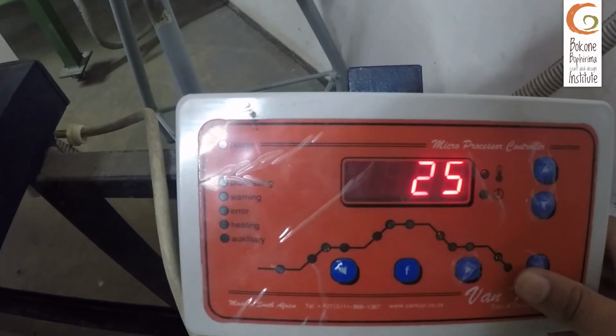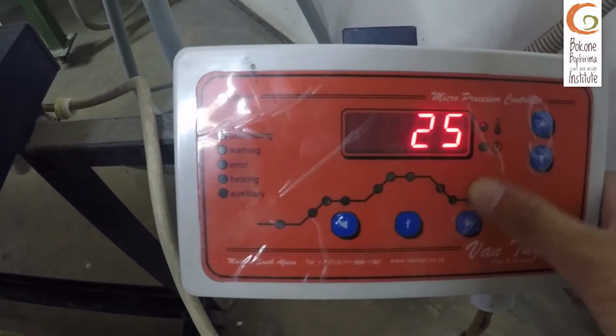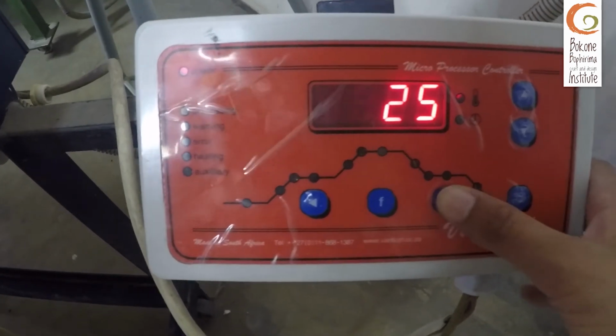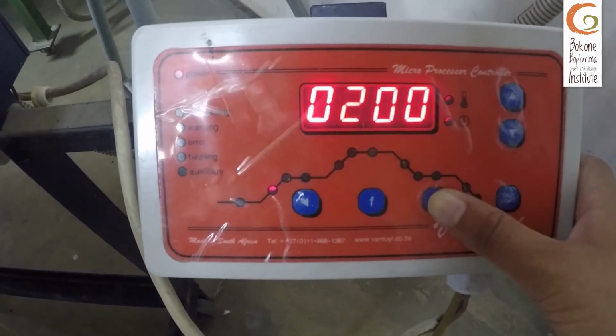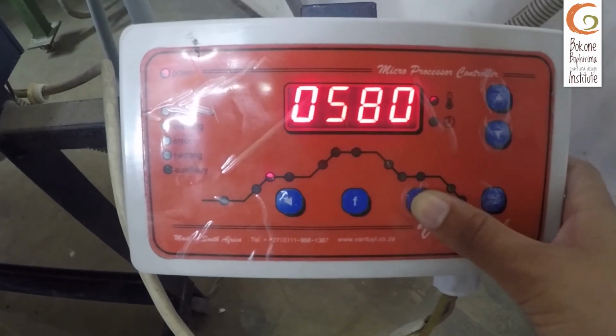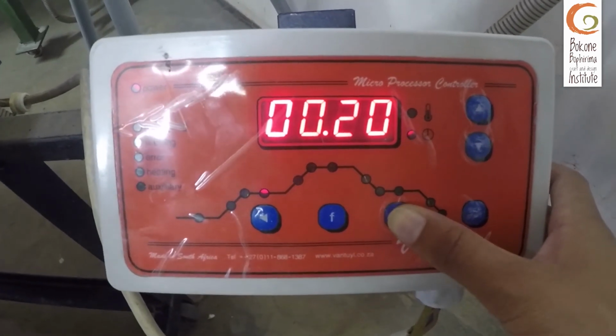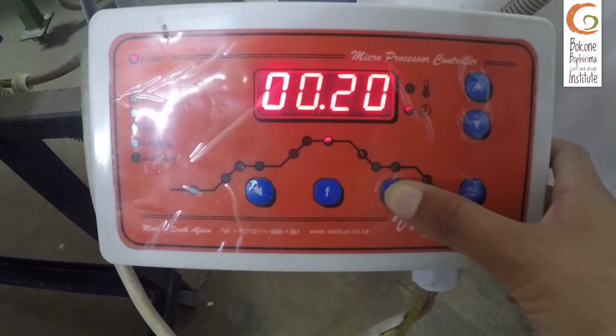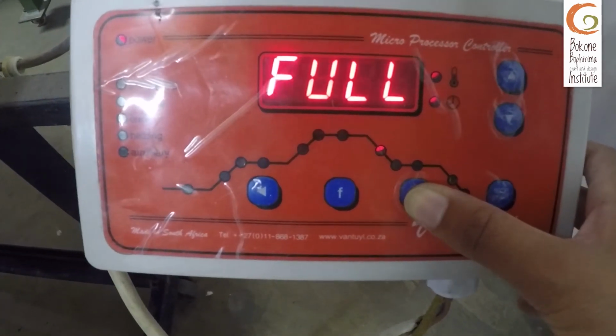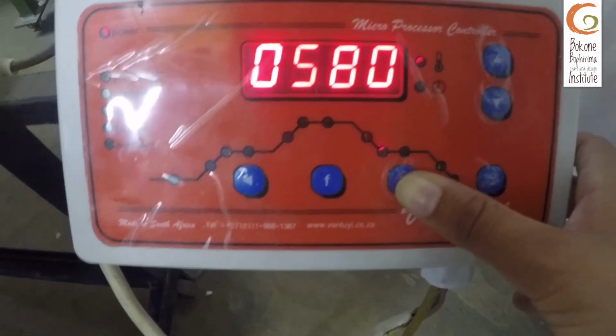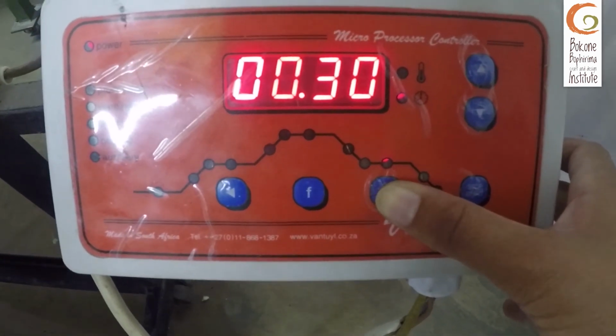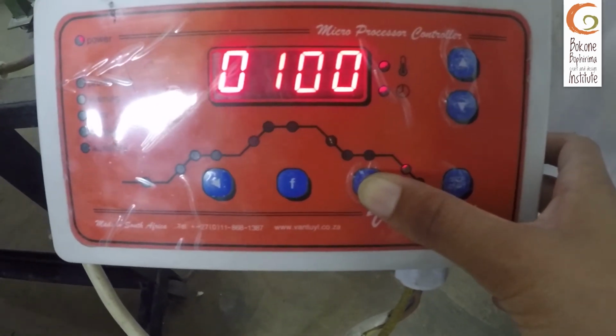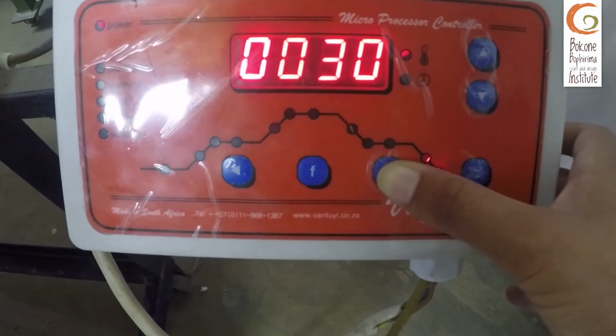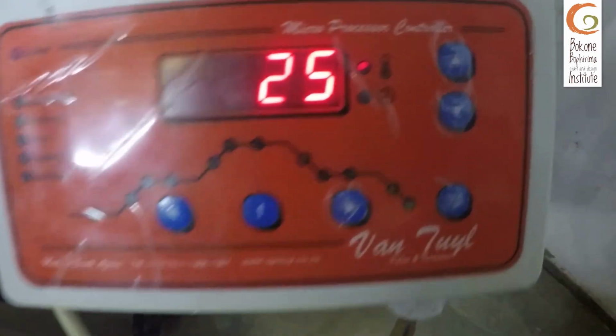We are now going to a kiln program where our temperature is reading 25 degrees Celsius, where we are starting immediately, going 200 degrees per hour to 580 degrees, dwelling for 20 minutes. Then we're going up the ramp at 250 degrees per hour to 680 degrees, which is our top temperature, soaking for 20 minutes, coming down at full to 580 degrees, soaking for 30 minutes, coming down at 100 to 30 degrees Celsius.